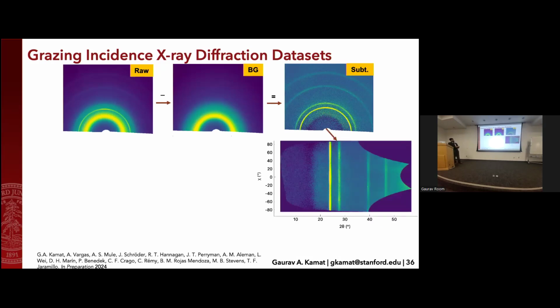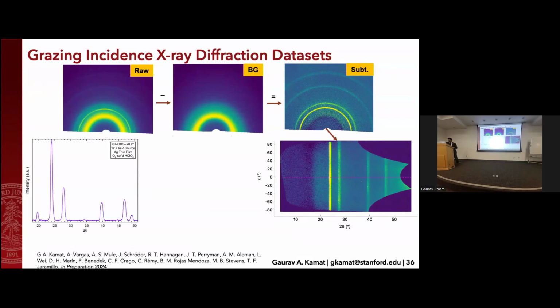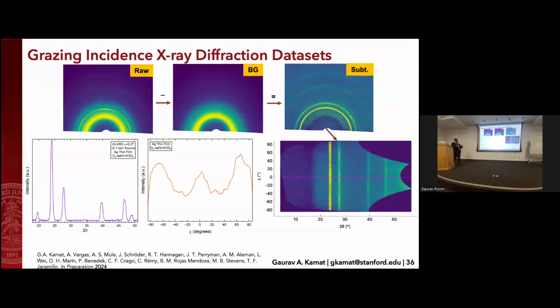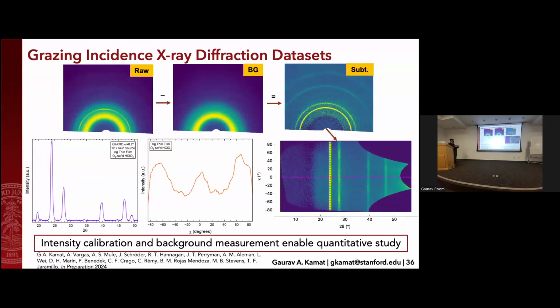If we do a little geometric transformation, instead of rings, we can turn these into lines. Now 2 theta versus chi is what you're looking at here. 2 theta is your main diffraction angle, and chi is sort of specular versus off-specular, which means is the outgoing X-ray in line or not in line with the incoming X-ray. If you take a horizontal line across this data and read it out, it looks a lot more like a traditional X-ray diffractogram that tells you about crystal structure. And if you take a vertical line, it can tell you a little bit about the surface texture and some information about the orientation of different facets of your material.